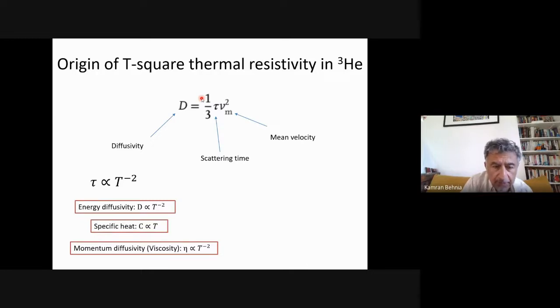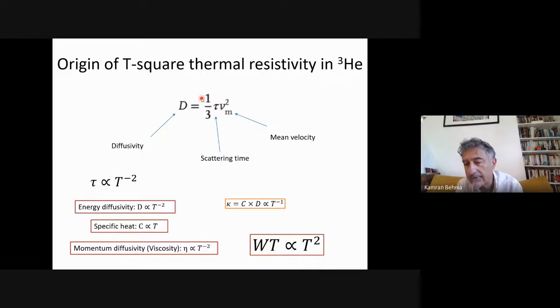Now, if you take this energy diffusivity and this specific heat, thermal conductivity is basically the product of these two. Specific heat is linear in temperature. Thermal diffusivity is proportional to T^-2. You end up having a thermal conductivity which is proportional to the inverse of temperature. And in the language of metal physicists, this is thermal resistivity, which is T squared.